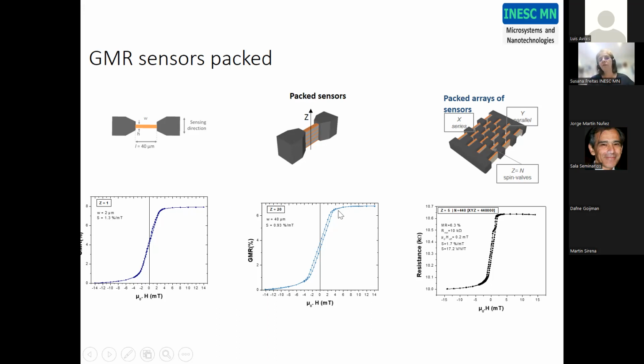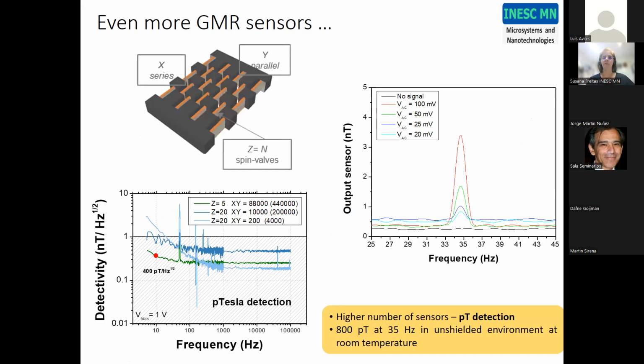And we have here the individual transfer curves. This is the resulting transfer curves. And here is the result for the series of vertically packed spin valve sensors. In this case, this is a GMR, it's not a tunnel device. It's a GMR because it's fully metallic transport. It's easier to build. So it means that we have done this and we could bring the noise down to picotesla at room temperature.